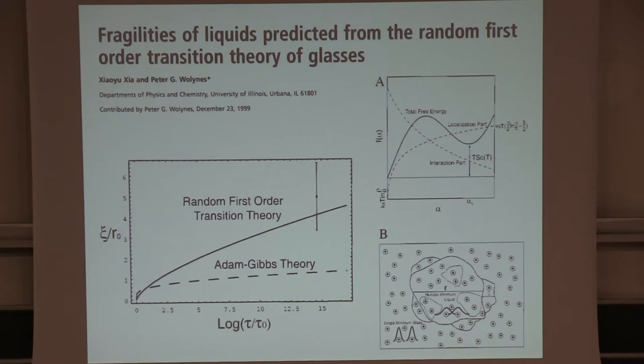You say that you're delocalized in one region, and the interface to the surrounding material is sharp. Of course, it's not sharp. That's why you get this weird exponent 2 over d. But if that were literally true, then you're able to calculate the surface tension by a simple argument saying that the surface tension is the same force that's finally giving you the vanishing of the entropy. It's, of course, an interaction term, but it must be that that interaction term is what's necessary to finally overcome the entropy at the standard glass transition itself, at the Kauzmann transition itself.